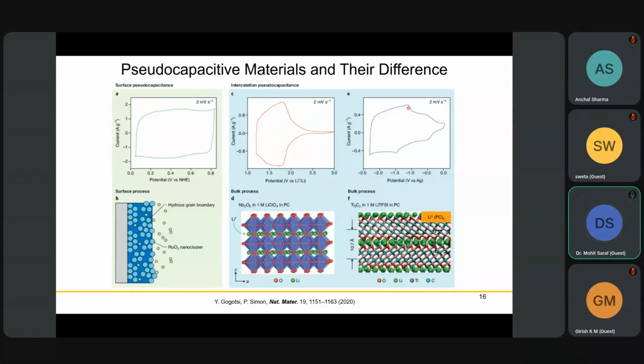At the same time, when you change the electrolyte, for example this MXene Ti3C2 in lithium TFSI in PC electrolyte, you see some expression of these redox peaks, but it does not follow the ideal rectangular behavior, so basically intercalation is happening. It's a kind of bulk process, whereas surface pseudocapacitance, which is very fast, is a surface process.